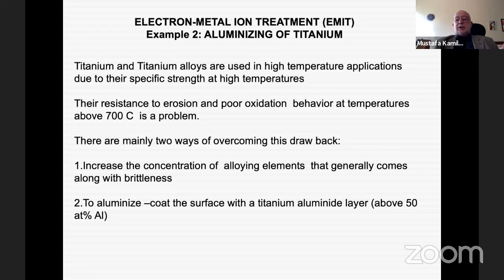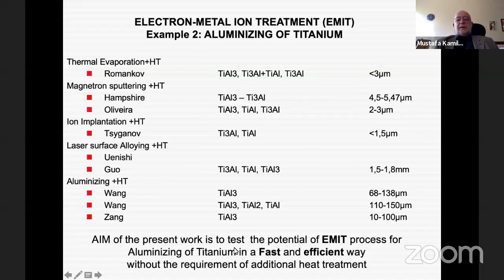So another way is to aluminize the coatings to produce an aluminide layer, especially for improving the oxidation resistance. And here you see the literature survey that has been conducted for aluminizing of titanium. As you see, standard deposition methods end up with very low coating thicknesses. Laser surface alloying and then heat treatment ends up with very thick layers. Aluminizing plus heat treatment also ends up with thick aluminide layers. So we try to understand this process and apply aluminizing by this method at different temperatures to observe the effect of this method on the production availability of aluminides of titanium.